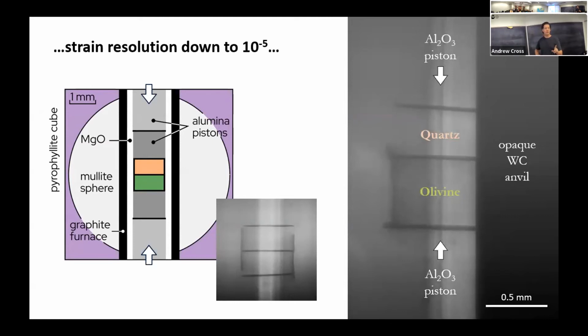So in addition to the energy dispersive X-ray diffraction patterns, we also get X-ray radiographs. And so here we're looking at our deformation cell. This whole cell that is inside a cube is about 6 millimeters in each direction. In a typical experiment, we have anvils on the left-hand side that have sintered diamond tips, so those are X-ray transparent. And then on the right-hand side, we have tungsten carbide anvils, so they're opaque to X-rays. To be able to see where our samples are precisely, we encase them in nickel foils. Those are dense and absorb a lot of X-rays, so they appear as dark lines on a radiograph.